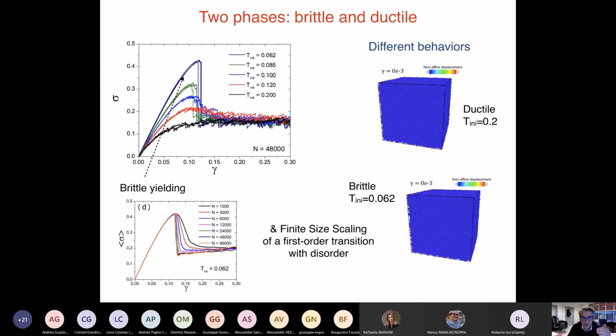So it really looks like there is a transition between a regime which corresponds to systems which are not well annealed, where there is no real yielding, it's a smooth change from elastic to plastic behavior, to a regime in which there is a phase transition between the two, which is discontinuous. I mean, there is a phase transition between the two regimes. This phase transition is discontinuous. So this is what is called brittle behavior. This is what is called ductile behavior.